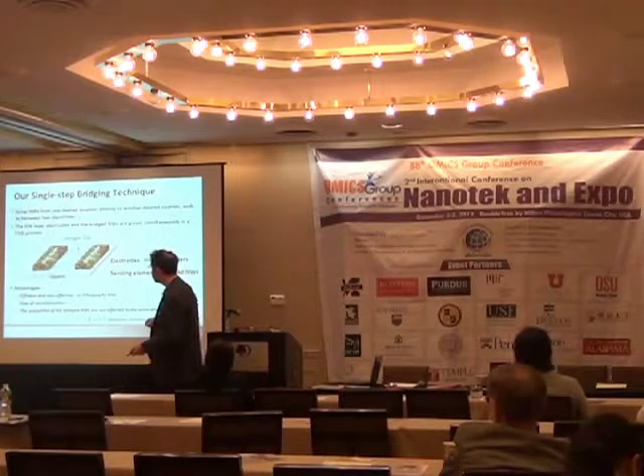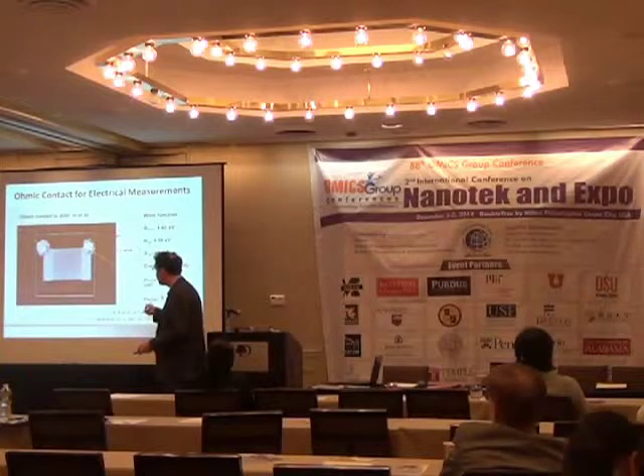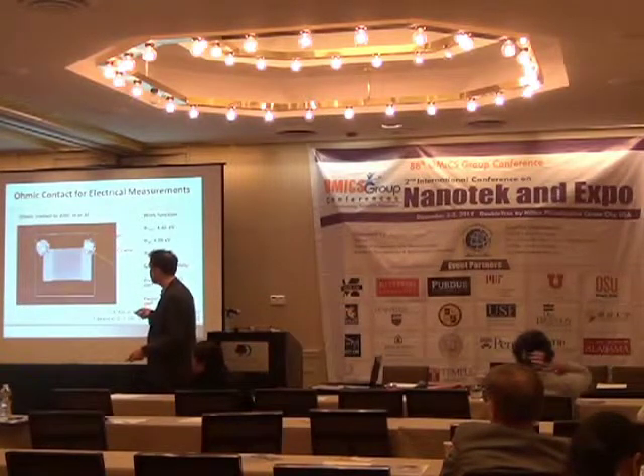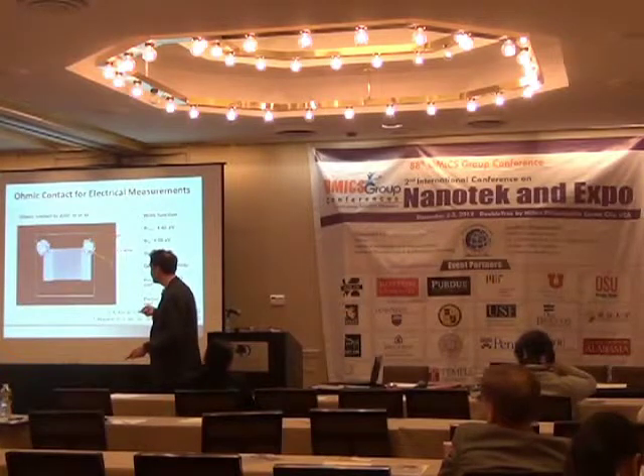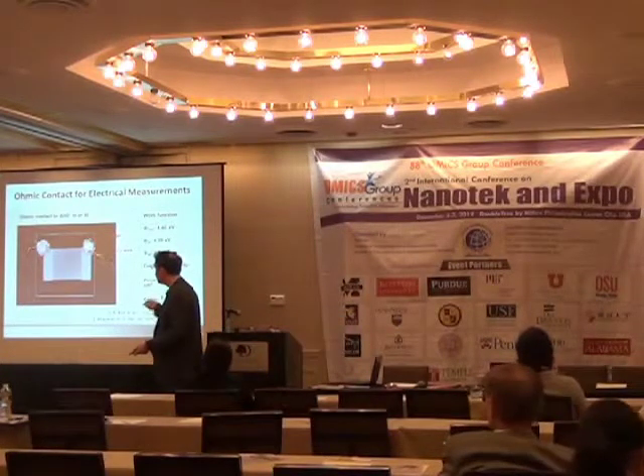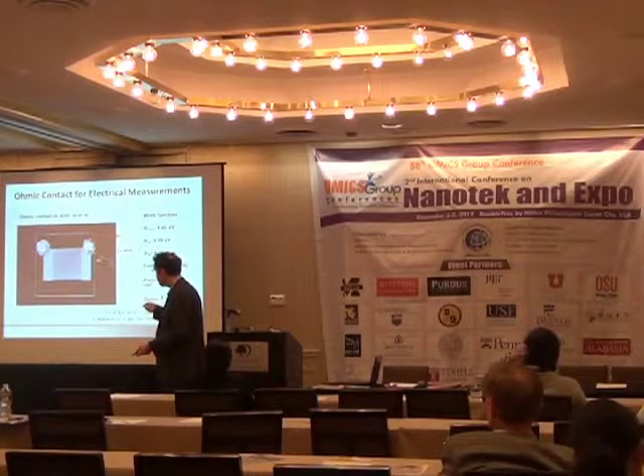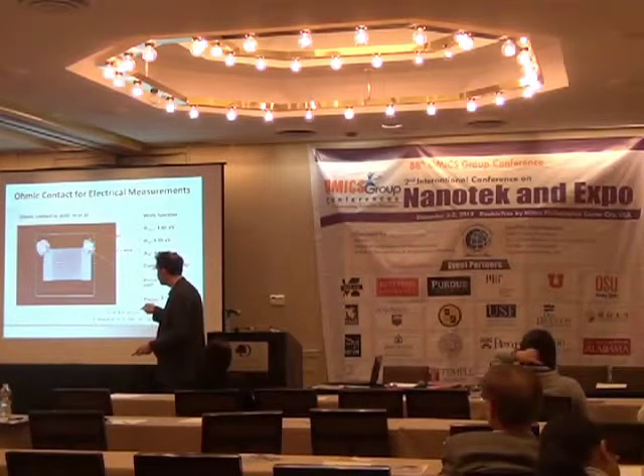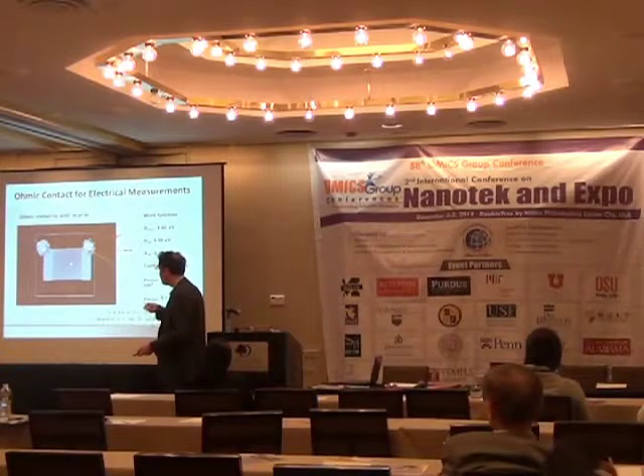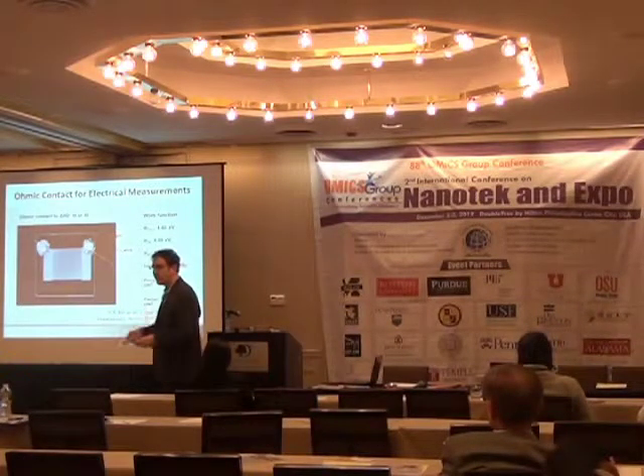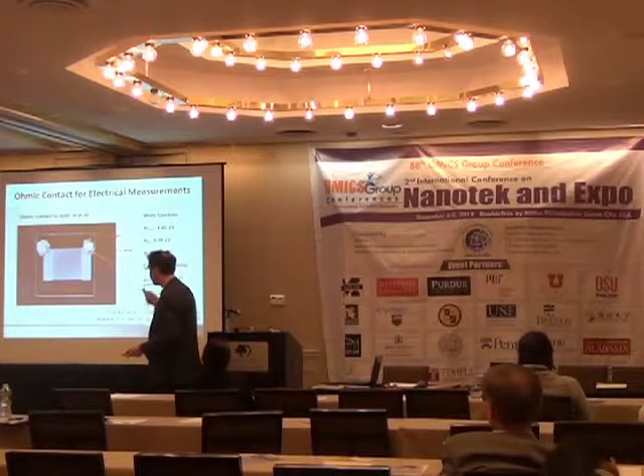This is just to show you that we actually make the sensor by ourselves. It's very easy, and then we can contact them like this. And this shows the contact, so you have the plus and the minus here, and the contact electrode here. In between, the part that is dark is just the bridge part that you don't see, because the nanowire density is very low.